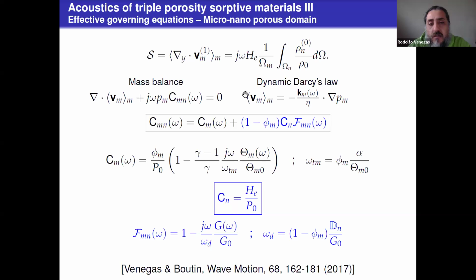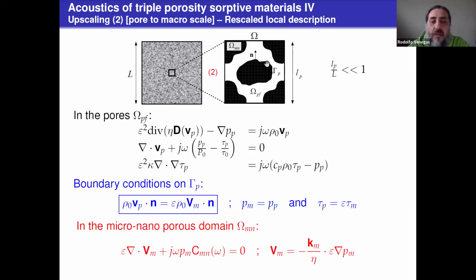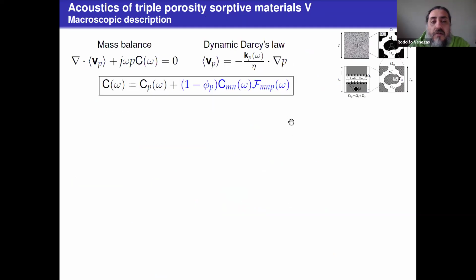So now that we have this macroscopic description for the first part of it, we use it and couple it with the Fourier-Stokes system to upscale the problem a second time in order to get up to the macroscopic scale. So in a similar way, we formulate a continuity of pressure, temperature, and also mass flux. And we upscale this set of equations to get a macroscopic description of the same type, but now compressibility has a contribution coming from the pores and from what is in black here, which accounts for the micropores and the nanopores that are inside this domain. And in this particular case, F accounts for pressure diffusion.